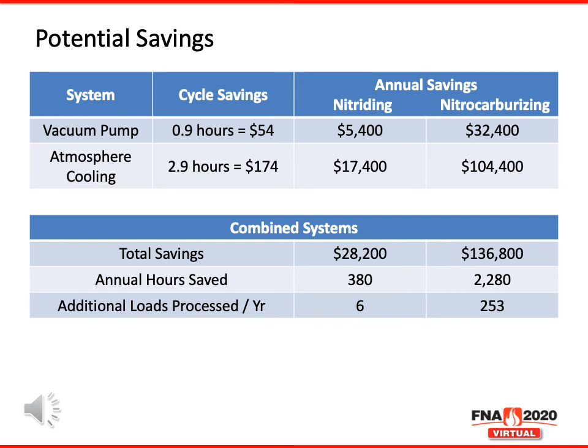So if we look at the combined systems, in total cost savings from an operating rate standpoint, exclusive nitride cycles are looking at potentially $28,000 a year in savings. From a nitrocarburizing standpoint, very significant, almost $137,000 worth of annual savings by adding these systems onto a furnace. If we look at it in terms of hours saved, again, looking at running the same number of cycles, but now at a faster or lower overall cycle time, you're looking at 380 hours from a nitriding standpoint, potentially 2,300 hours from a nitrocarburizing standpoint.